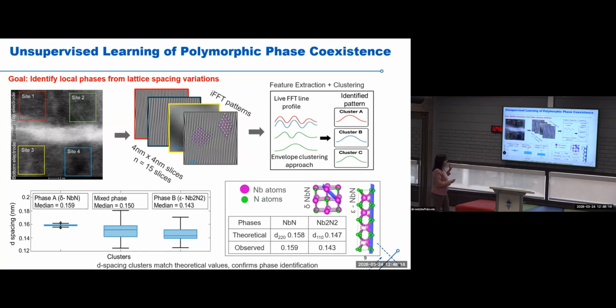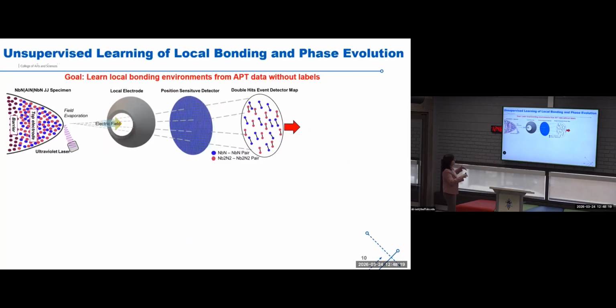So how these phases are found, because this is not enough for our curiosity. So then we did advanced analysis in APT. In APT, we actually get atom positions, and those atom positions are cloud data. So basically, you can go back, extract that cloud data, and perform algorithms to get more information. So what we did, we took the detector data, where we can see the pair separation for individual atoms. So niobium to nitrogen bond, Nb2N2 bond.